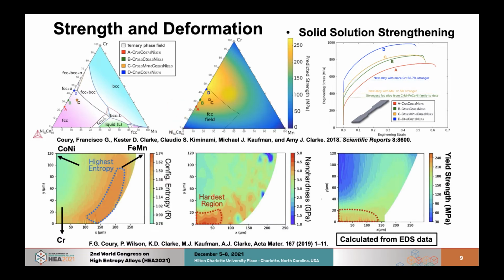And this is also well shown by this study that we performed on a diffusion multiple. So this is basically a compositionally graded sample that we have, on this end here cobalt nickel, on this end here iron manganese, and down here chrome. So we can clearly see that the highest entropy region does not match at all with the hardest region. So this is all single phase FCC. And we see that the strongest region is really when we go from cobalt nickel to chrome, as shown by Varvenne's model. So in this figure here, we basically took EDS data from the whole area and applied Varvenne's model, and we can see that it explains very well the experimental data. So we really think using these types of predictive models is a very strong way to develop new alloys.